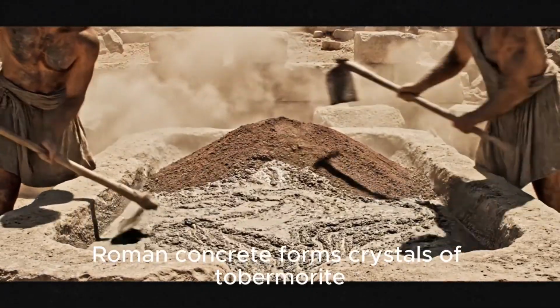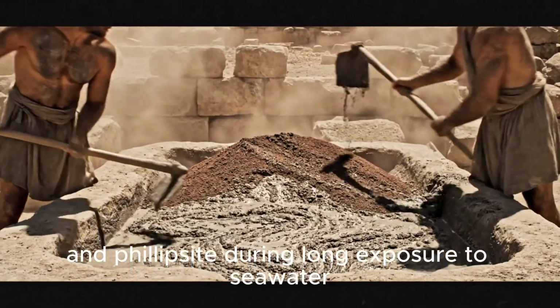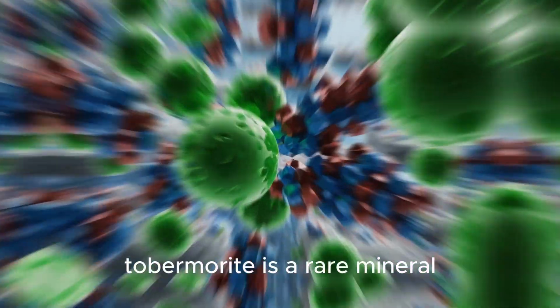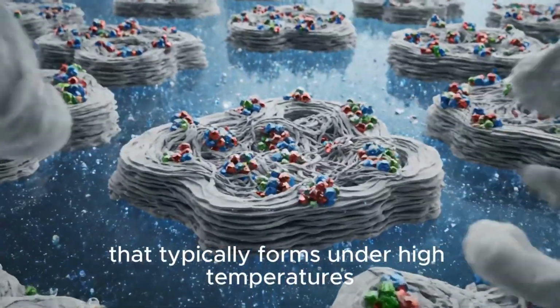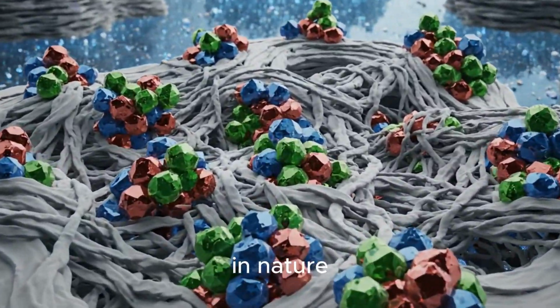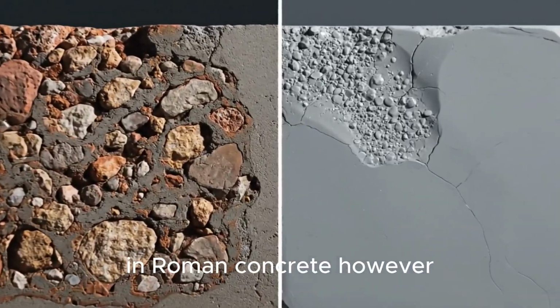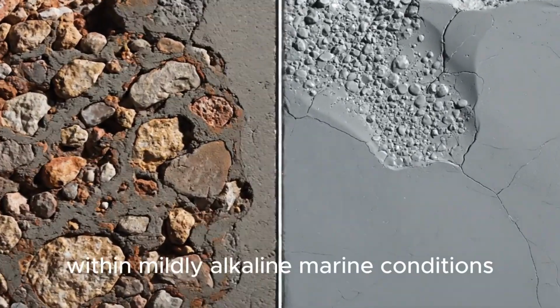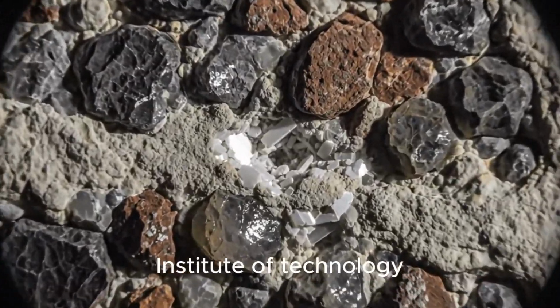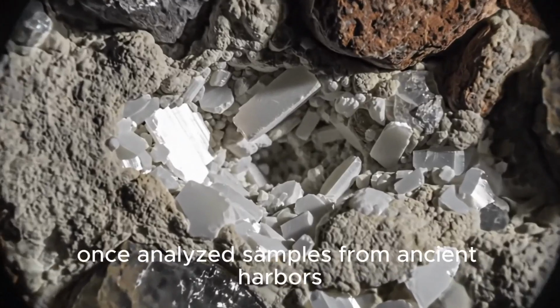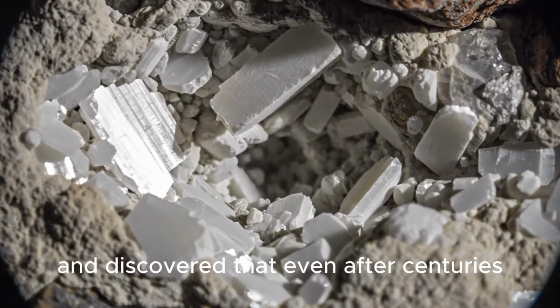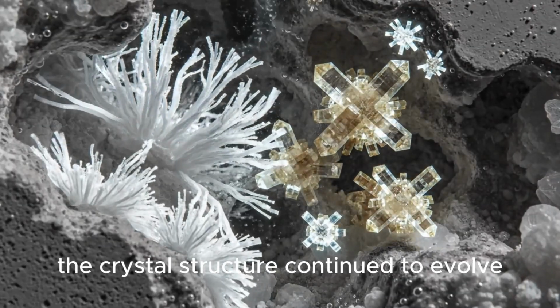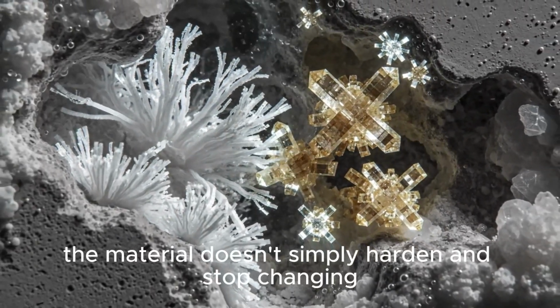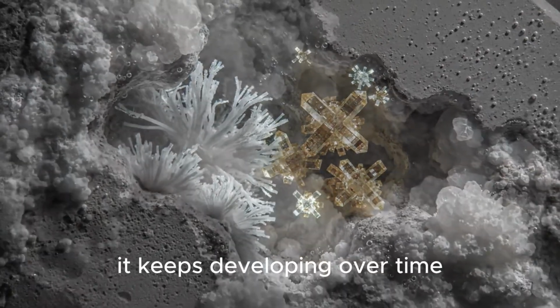Roman concrete forms crystals of tobermorite and philipsite during long exposure to seawater. Tobermorite is a rare mineral that typically forms under high temperatures in nature. In Roman concrete, it grows slowly within mildly alkaline marine conditions. Researchers from the Massachusetts Institute of Technology once analyzed samples from ancient harbors and discovered that even after centuries, the crystal structure continued to evolve. The material doesn't simply harden and stop changing, it keeps developing over time.